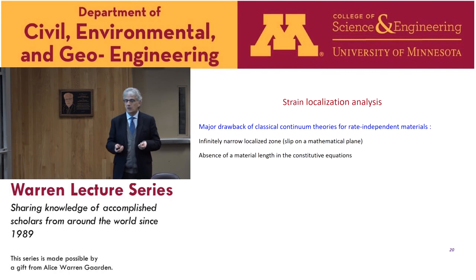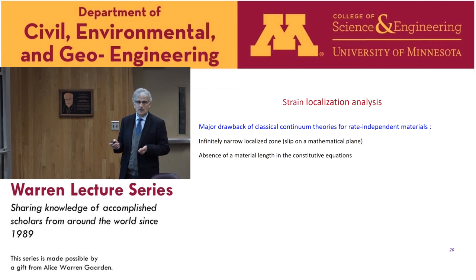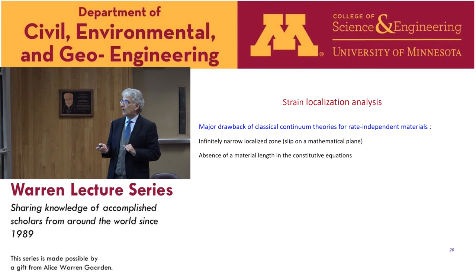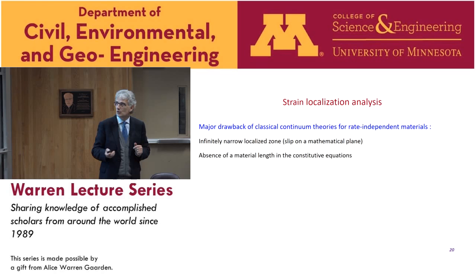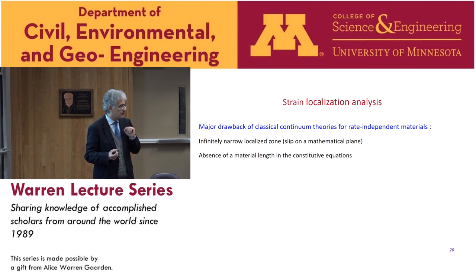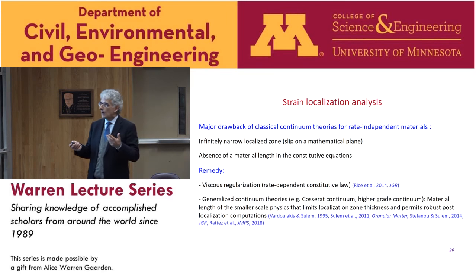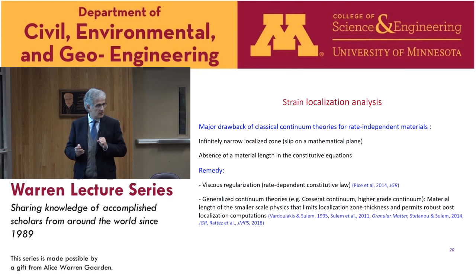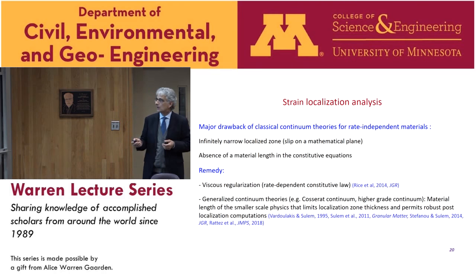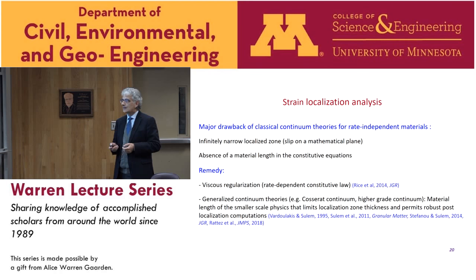We know also from the pioneering work of Yannis Vardoulakis that a major drawback of the classical continuum theories for rate-independent materials is that it leads to an infinitely small localized zone, which corresponds to a slip on a mathematical plane, which is non-physical, and doesn't correspond to the observations also. And this can be traced to the absence of a material length in the constitutive equations that could limit the actual thickness of the localized zone. At least the grain size is a limiter for the localized zone. And then the remedies are known: either introduce a viscous term, called viscous regularization, so considering a rate-dependent constitutive law or the framework of viscoplasticity, or resorting to generalized continuum theories, Cosserat, higher order grade, where we will introduce information at a lower scale